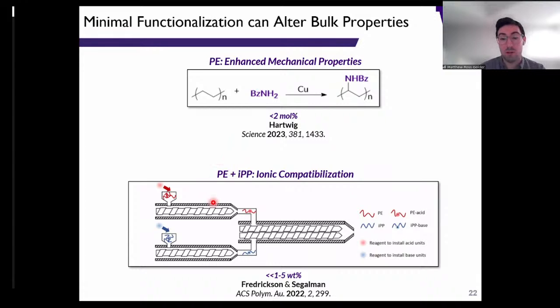So in this case, polyethylene and isotactic polypropylene with positively charged and negatively charged groups, and you can form these ionic pairings. In just really, really small amounts of those pairings, less than 1 to 5%, depending on the specific identities, can lead to complete compatibilization.